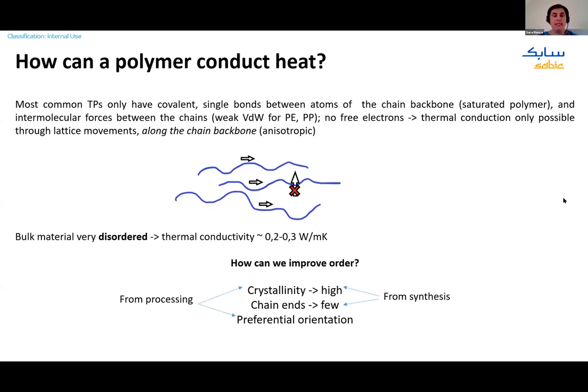Now, the problem is that bulk polymers are very disordered. So the thermal conductivity that you can read in a bulk polymer is in the order of 0.2 to 0.3 watt per meter Kelvin. The point is, how can we improve this? There are three main elements to consider. We should have high crystallinity, so a simple repeating structure and a regular structure. We need as few chain ends as possible, so very long chains, and we need a preferential orientation of these chains.